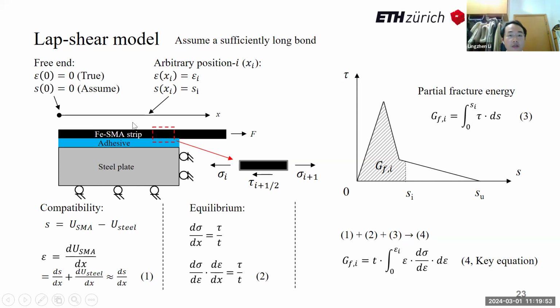Here, I assumed a sufficiently long bond length so that the load at the right-hand side doesn't introduce any shear deformation and shear stress at the free end. Here is the boundary condition. At an arbitrary location xi, the slip is written as Si. Tensile strain in the adherend strip is written as epsilon i. I considered the compatibility written here, the equilibrium of the adherend strip, and also the fracture behavior in the bond line.